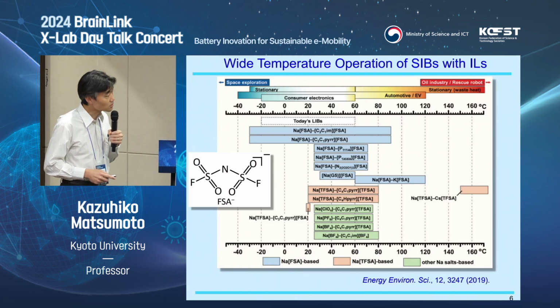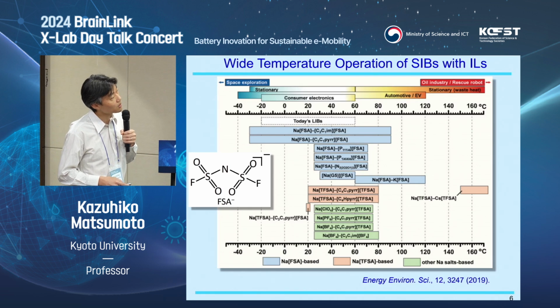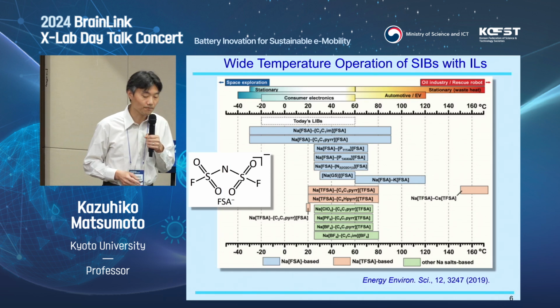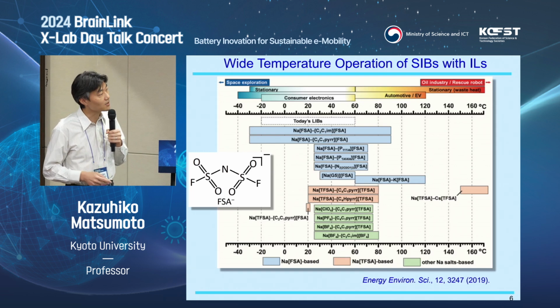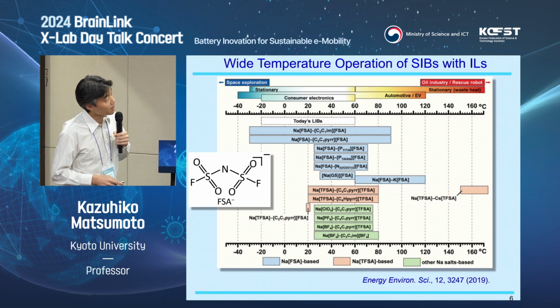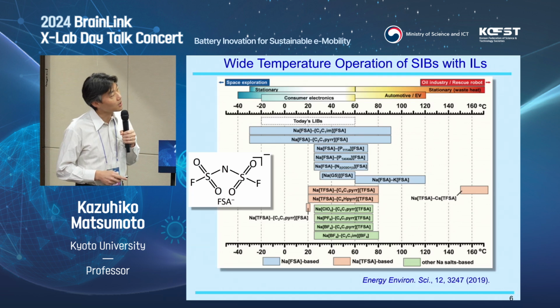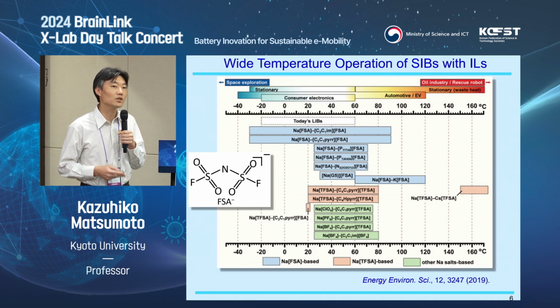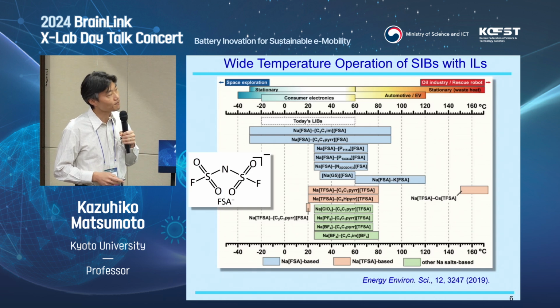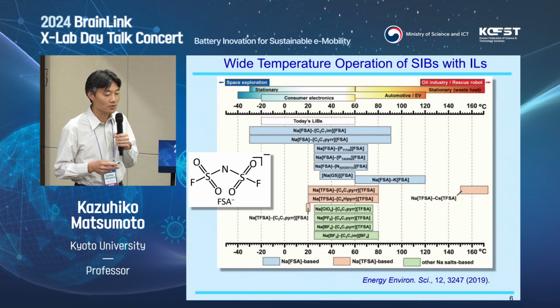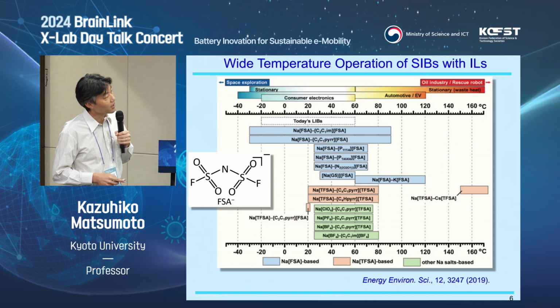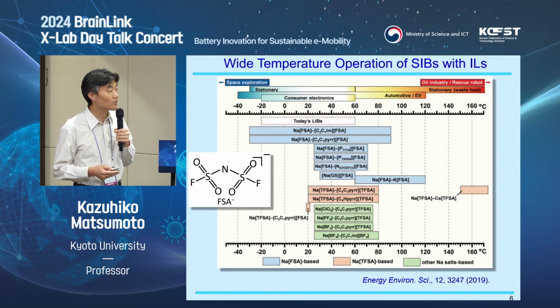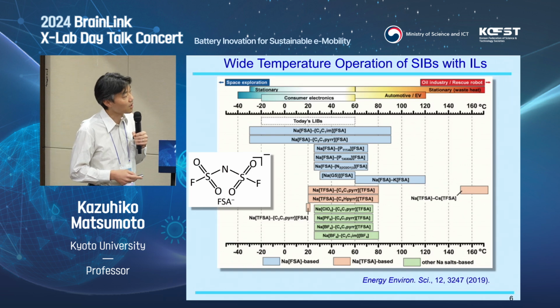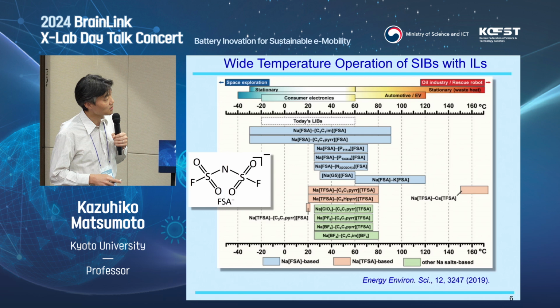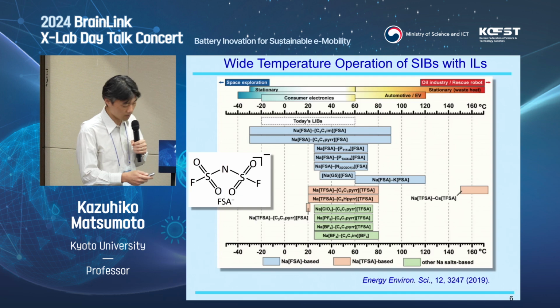But by using ionic liquids, we can extend the temperature range, and we typically work around 90 degrees C because sodium metal melts above that temperature. And then we call it the intermediate temperature. So we can use materials which we use around room temperature, without using special materials. And also we can get some waste heat from industry and even from vehicles, cars. And typically an ionic species is this FSA anion, where we have 2 fluorine on the sulfonyl amide type of structure.